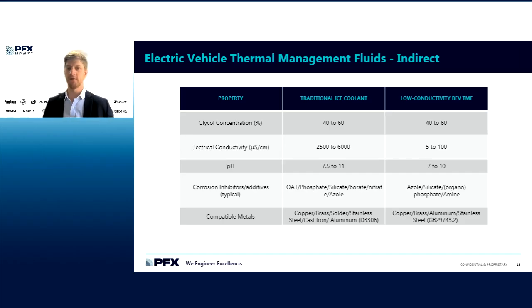due to the conductivity contribution that would come with those additives. Another place where we see a little bit of deviation is in the corrosion inhibitors or additives that are used. So the primary contribution to electrical conductivity in a coolant or a heat transfer fluid comes from the additives or the corrosion inhibitors that are in there.